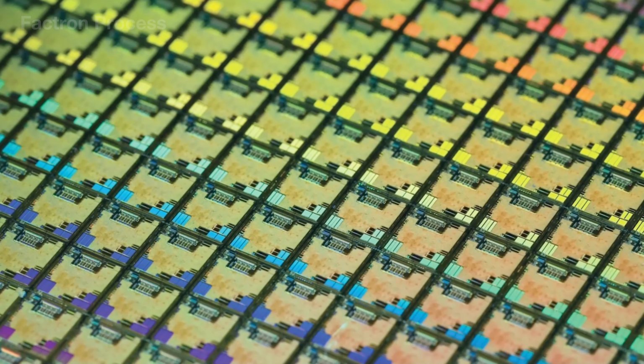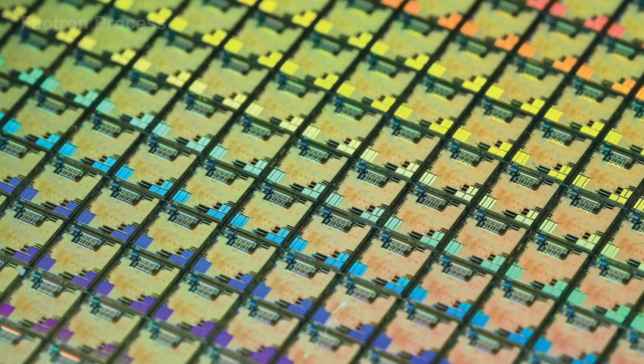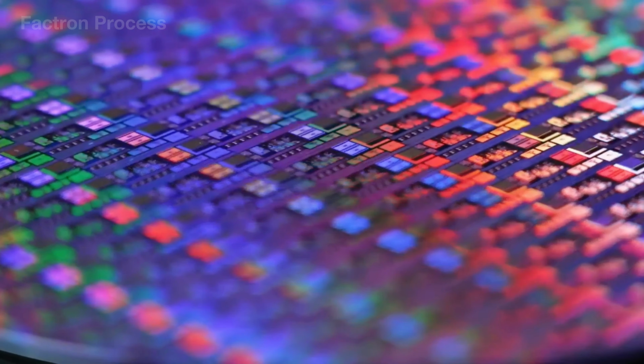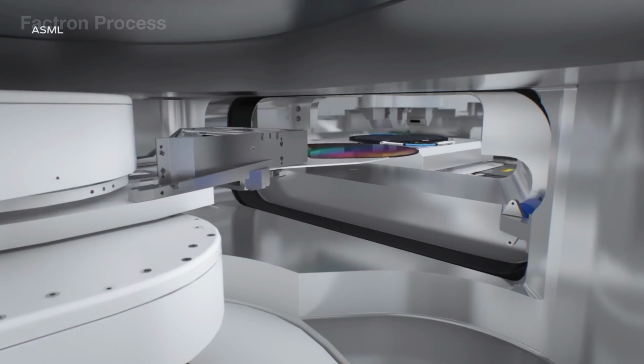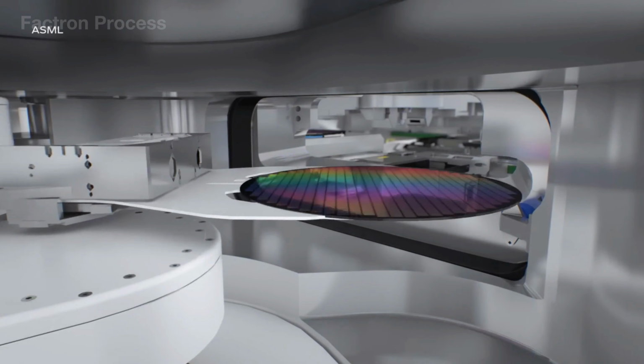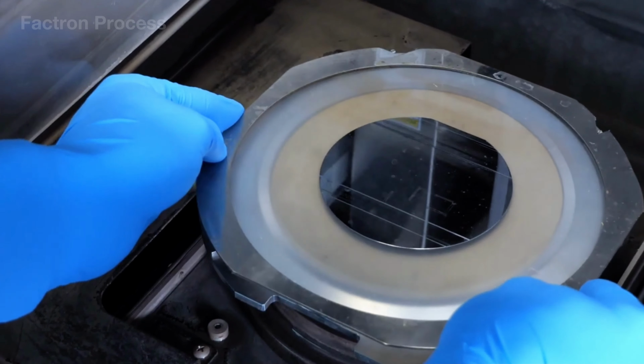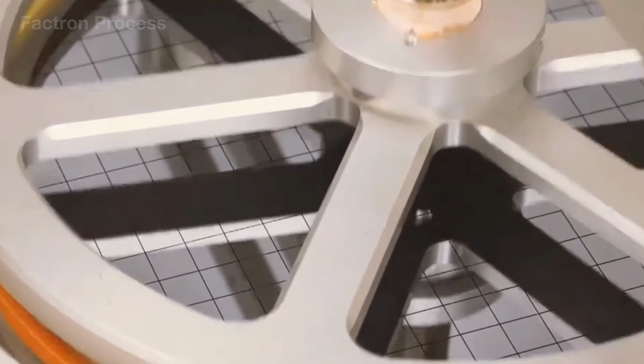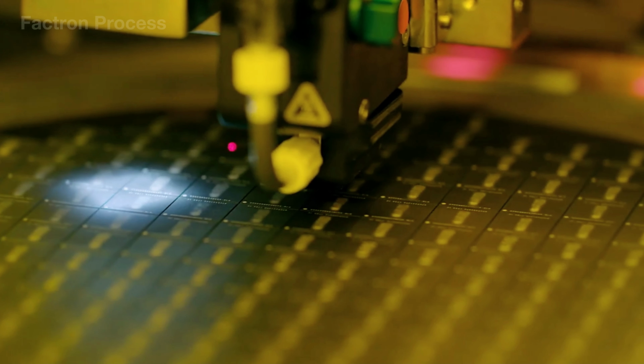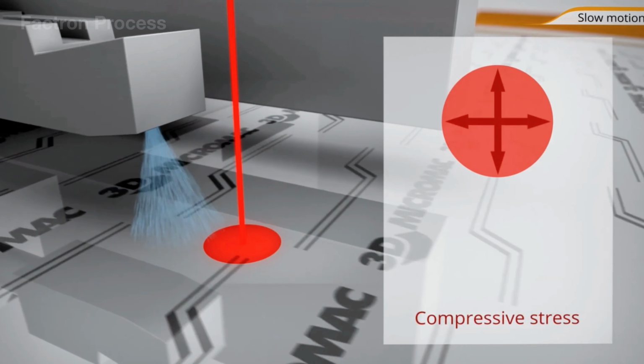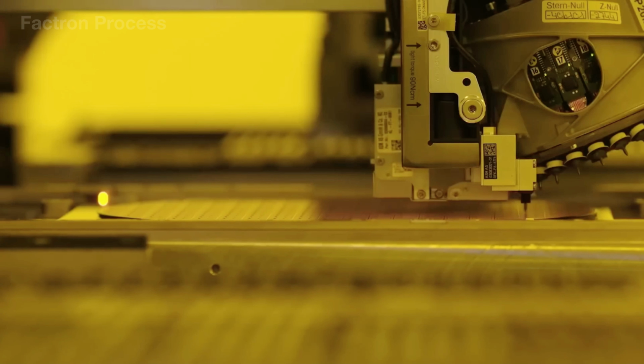However, they are still connected on the same sapphire substrate and cannot yet be used individually. To separate them, the wafer is loaded into a cutting machine equipped with an ultra-thin diamond blade or a highly precise laser. The system cuts along predefined lines between the chips with an accuracy of only a few micrometers. Even a slight deviation can crack the chip or cut into the light-emitting region, rendering the entire device unusable.